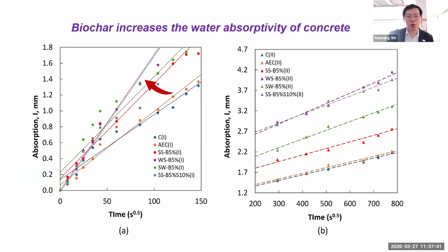Here's the bad news. When we incorporate biochar, we do see an increase in water absorptivity. This x-axis, the first one, is between 0 to 150, but remember this is a square root of the time. So basically this is an indication of the micropores, the capillary action taking water from the adjacent environment. And the secondary absorption also increased, which is typically water coming from the environment into the concrete and filling the larger pores. So this is a concern, but there are tools such as admixtures that can help reduce this water absorption.